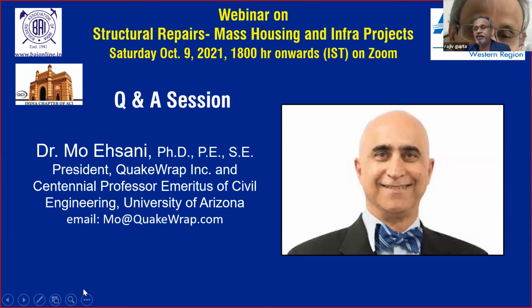So do you really recommend this for general construction? I should tell you that one of the problems with FRP products is that in general, they have much lower modulus of elasticity compared to steel, for example. So I would say that in most cases, they don't become very economical for new construction. But when it comes to repair and strengthening, like we are using here, then they become really economical and they can beat a lot of other conventional repair systems.